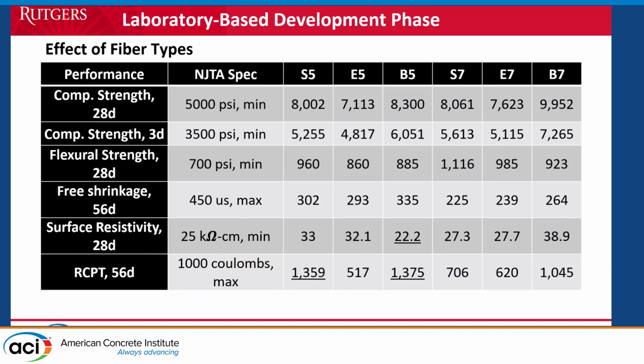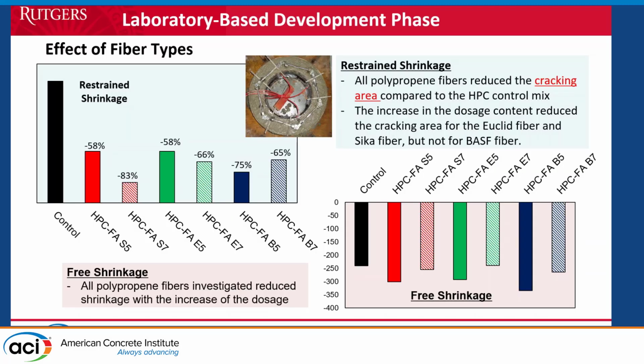They require the compressive strength at 28 days and at 3 days, and flexure strength. About 4 years ago, we also tried to replace the rapid chloride permeability. By now, they do what they call the surface resistivity study, so we ended up putting this part in the study. If you look at the quick results, only a few mixes did not satisfy the standard specs. You can see this B5 mix and this S5 mix. All the others were within the limits.